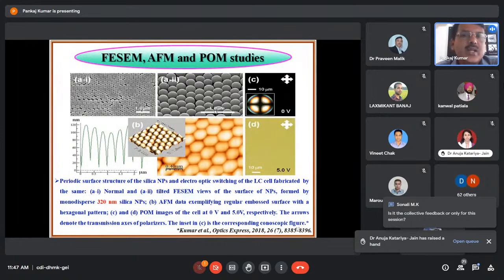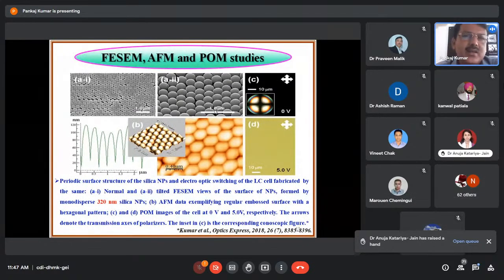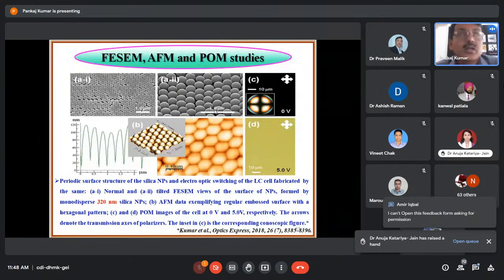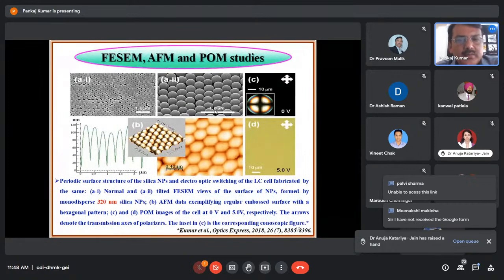In figure C, you can see the conoscopic image as well as the dark image at 0 voltage. This is the liquid crystal cell made from these coated glass plates, and you can see a perfectly dark state here. In figure D, you can see the white state. Although it is not fully the white state, if we increase the voltage more, then it will go to the perfectly white state.